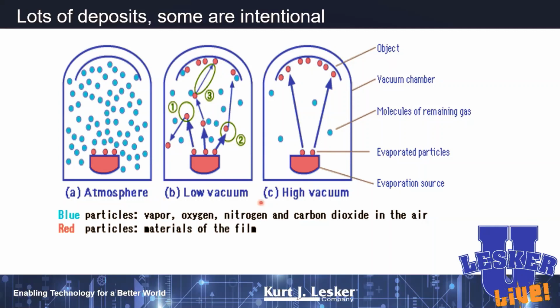As we go down in pressure, though, maybe we get down to maybe 10 to the minus 4 torr or so. We've eliminated a lot of those molecules, and we do now start to open up some pathways here, but we're still going to have lots of collisions. And so the aluminum molecules that get here won't have much energy. Most likely they will have collided with some oxygen or some nitrogen in that path, and you'll make aluminum nitride or aluminum oxide. Not a great reflector. It's only once we're in high vacuum that we've got these big open mean free paths, and we have some right to expect that we can make a pristine thin film. Again, most of your automotive lighting manufacturers are doing their depositions about in here, and that's why a lot of these films are pretty junky.